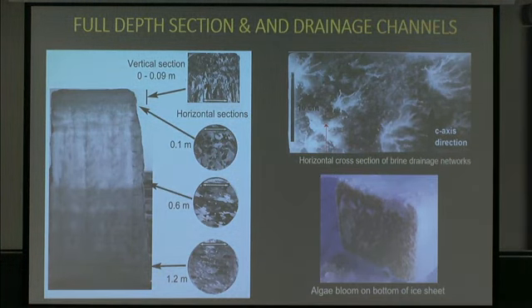One final thing on this. Erlen showed a nice photo before. What we see when we do experiments in the field, and particularly fracture experiments, is that these channels are regions of weakness. So if you're propagating a crack through material like this, the crack will preferentially go and root itself through these areas. So you wind up with a very unplanar crack front. Here's what an algae bloom looks like. We ran into those on occasion. And it can be a lot more prolific than this, actually.